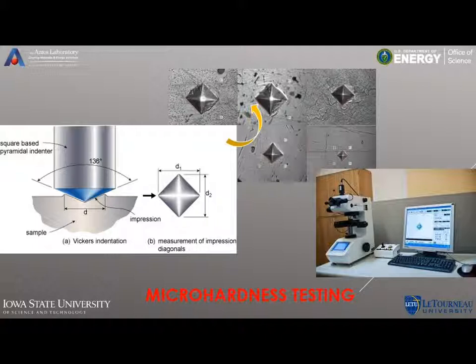Now onto some of the analysis here. Also in microhardness testing. The microhardness testing basically works by having this indenter come down, and it had a very sharp tip made out of a diamond fragment. And that was also shaped in a diamond pattern. And this would be lowered down into the surface of the material and then raised up. And then you would measure the distances between the points. And the computer software would take those distances and calculate the hardness based on the known weight applied to the